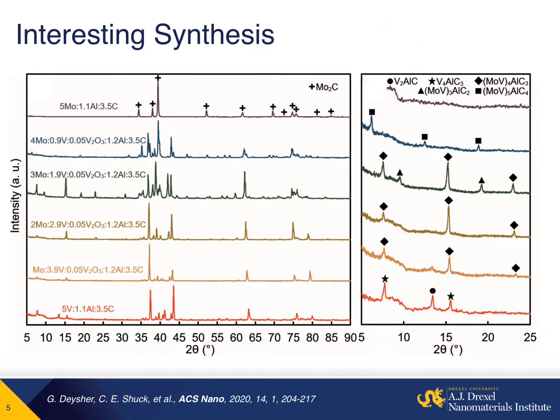Within the molybdenum vanadium system, we initially saw a wide variety of different MAX phases that could occur. MAX phases have the P63/mmc crystal structure, and in these phases specifically, the c lattice parameter is significantly larger than the a lattice parameter. Moreover, the c lattice parameter is very dependent on the number of transition metal layers, so the MX layers in MAX phases themselves. What this means is as we get thicker MAX phase structures, the 002 peak, which is characteristic of the c lattice parameter, gets larger and larger, so it shifts to the left in MAX phases.